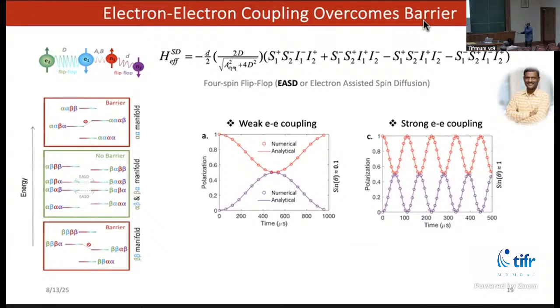And what we can see here is these plots, they show the flip-flop between two nuclei. On the left-hand side, when the coupling between two electrons is weak, the rate of flip-flop or polarization exchange is slow as compared to if the coupling is strong. So by having strongly coupled electron spins, a biradical, it's possible to have faster spin diffusion.